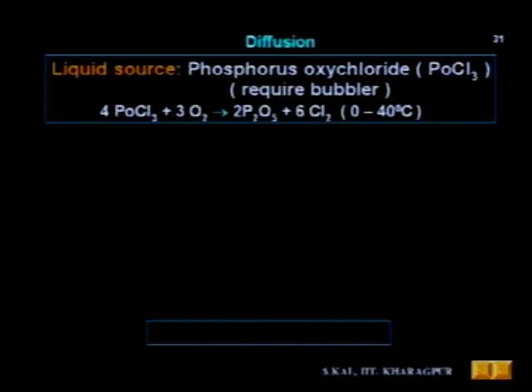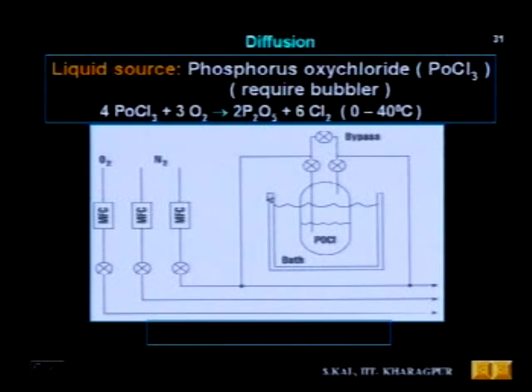Okay. Now, all the liquid sources require some bubbler, and the bubbler arrangement is shown here. A typical bubbler arrangement is shown here, because if the source is in liquid form, how is the liquid brought near the surface of the silicon? Obviously, it has to be in the form of vapor. So that liquid source POCl3, first you have to vaporize it, and the POCl3 vapor will flow into the diffusion tube, where it will react with silicon to form the phosphorus atom and silicon dioxide.